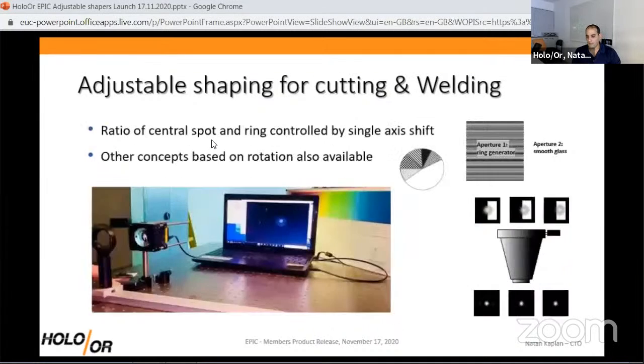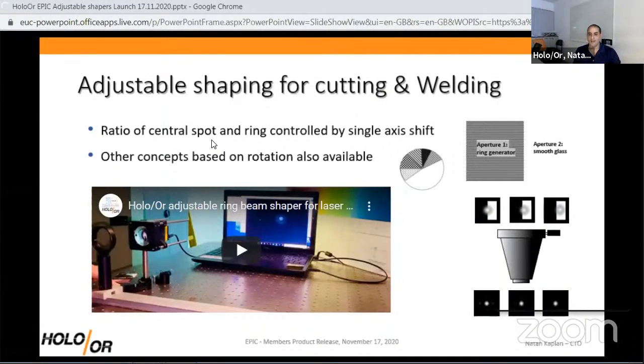So for that, we have a solution based on diffractive optics, which is basically the idea of using a diffractive optics sub-aperture element, which has a part of the aperture having a diffractive pattern that generates, in this case, a ring, while the other part of the aperture generates, in this case, zero order. It could be a different shape, for example, another ring, or splitting into two orders that you play with. And by moving the laser beam over the apertures, in this case simple mechanical translation would do, you can get different power to the ring or the center. Or for example, if it was double spot welding, you could get more power to the right spot or the left spot. A lot of variability is possible.